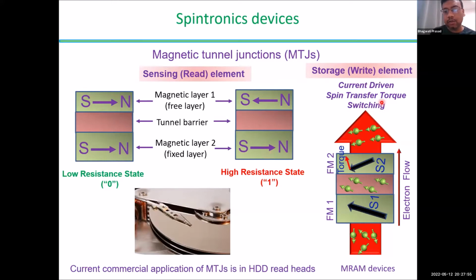So recently, or it's not recently, it's almost more than 10 years now, the concept called spin transfer torque came. So current driven switching. Basically what happens here is that when you flow unpolarized current through a ferromagnetic metal, it gets spin polarized. Okay, and then these electrons tunnel through the thin insulator barrier, and when they interact with the electrons of the other ferromagnetic metal electrode here, they can transfer the spin angular momentum. Depending upon which way you flow the current, you can basically manipulate the magnetic state of this free layer, this ferromagnetic layer, one way or the other, basically make them parallel or anti-parallel, and that way you can manipulate the state. So this is a very nice concept, and one can really make very dense devices and put them very close, so you can have a high density memory device with that.